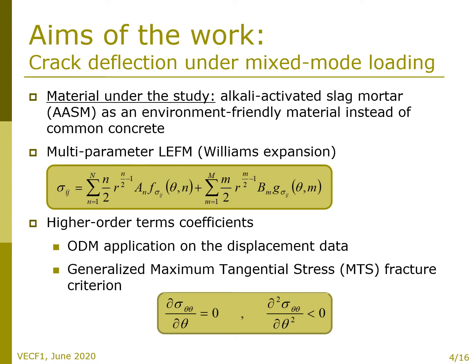The main aim of the work is to investigate crack deflection under mixed mode loading and to assess the importance of the higher order terms of the Williams expansion for description of this behavior. Crack deflection angles were observed based on the experimental campaign as well as calculated numerically from generalized maximum tangential stress criterion.